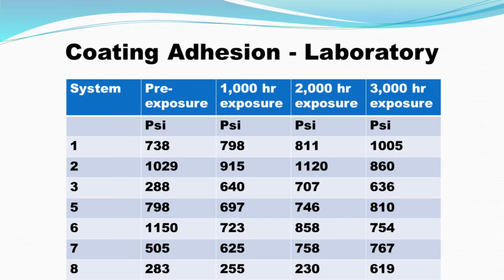In the laboratory, again, we have better control of the concrete specimens and better control of the surface preparation. So you got higher adhesion rates, but again, these were predominantly cohesive failures of the substrate.